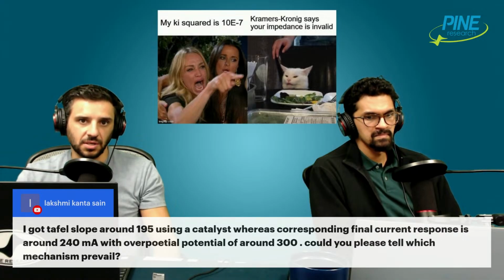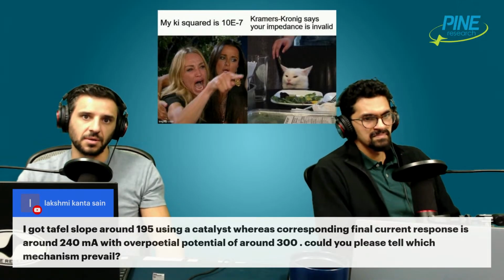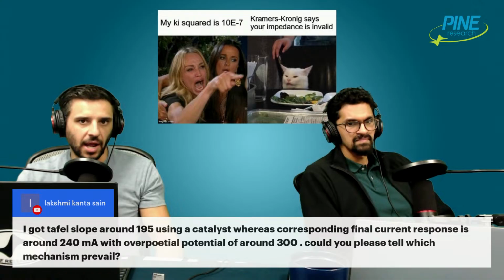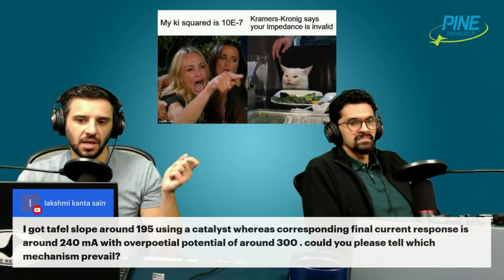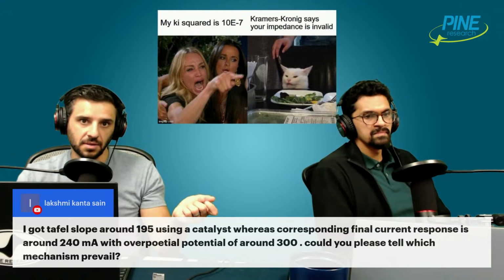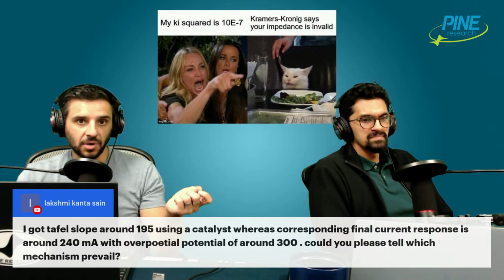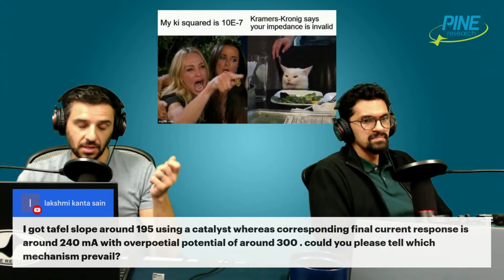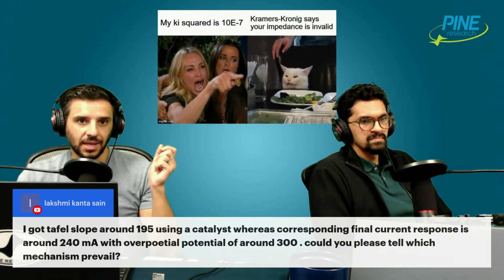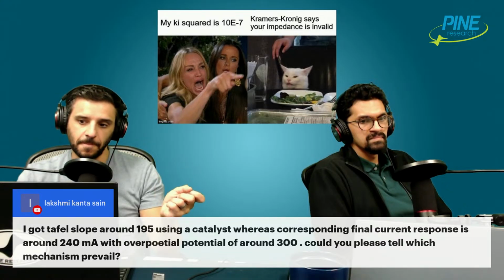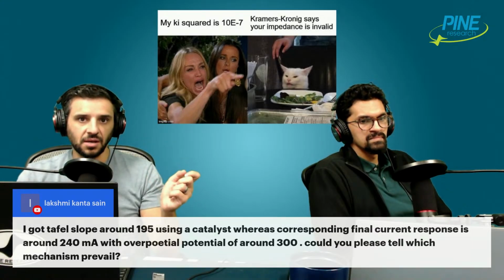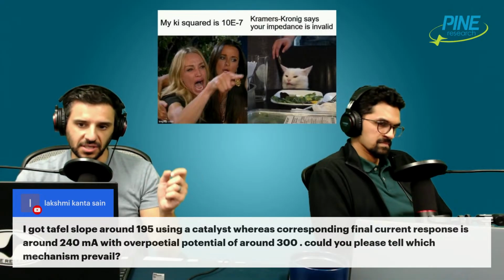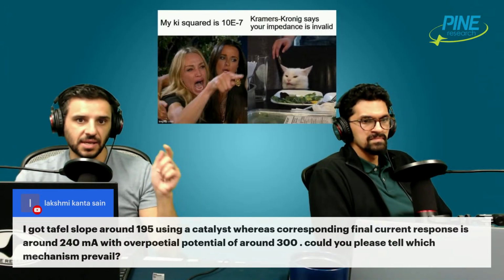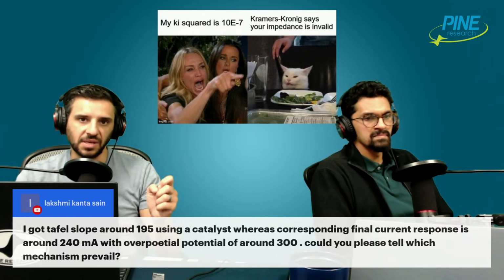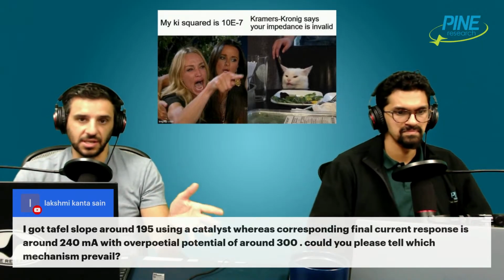The Tafel equation and the Tafel slope is a direct derivation of the Butler-Volmer equation. The Butler-Volmer equation describes how kinetic current and overpotential are related. I repeat, the Butler-Volmer equation, and by extension, the Tafel equation, and by extension, the Tafel slope, relate kinetic current to overpotential. So if the data from which you made a Tafel plot and then got the Tafel slope was not 100% kinetic data, your Tafel slope means nothing. It just doesn't. It doesn't mean anything.